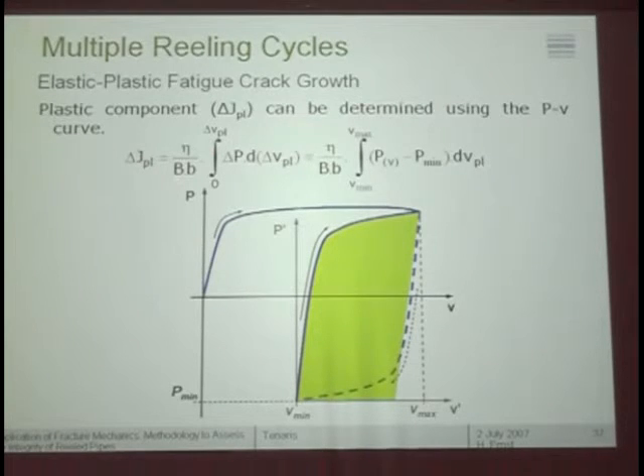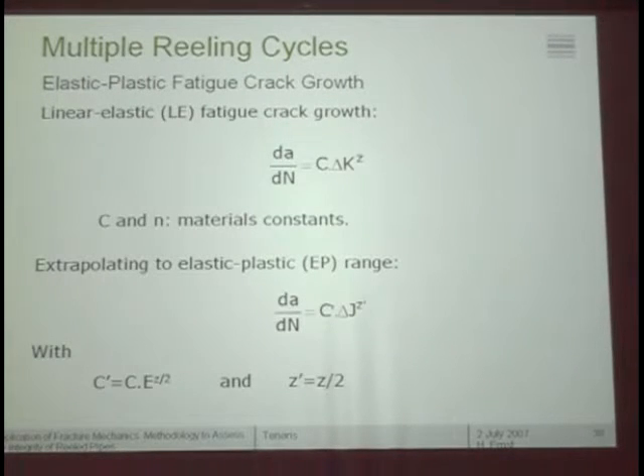J is usually eta over B times b, times the area under the load displacement record, for the plastic part, say, we are talking about the plastic part. So now if you have this test record going from 0 to this point, unloading, and back up again to the same point, the delta J is related now to delta P, delta V, which means basically it has to be associated with this whole area over here. And basically we sort of use the same idea of the Paris fatigue law, except that we alter a little bit the constants to have it in terms of delta J instead of delta K.